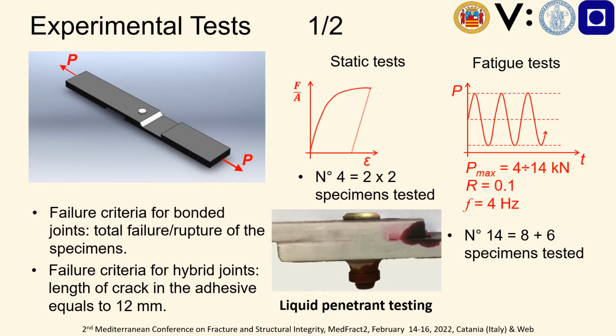Concerning the experimental test, two types of tests were performed, the static test and the fatigue test. In particular, concerning the static test, 4 tests were performed, 2 for the bonded joints and 2 for the hybrid joints. Whilst concerning the fatigue test, 8 tests were performed on the bonded joints and 6 on hybrid joints. The bonded joints were considered failed when they collapsed, while the failure criterion used for hybrid joints concerned the propagation of cracks inside the adhesive layer, and in particular when such cracks reach a value of 12 mm, which was measured through the liquid penetrant testing method.